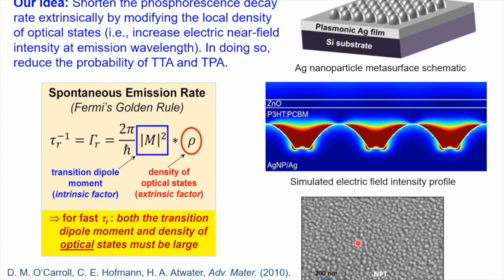We've been making these nanoparticle metasurfaces using a thermally assisted dewetting method, and we can control the size to some extent. Overall, the periodicity is not really there. These are aperiodic, but that's fine for this application. We were only concerned with short-range interactions between the emitters and the nanoparticles of the metasurface.